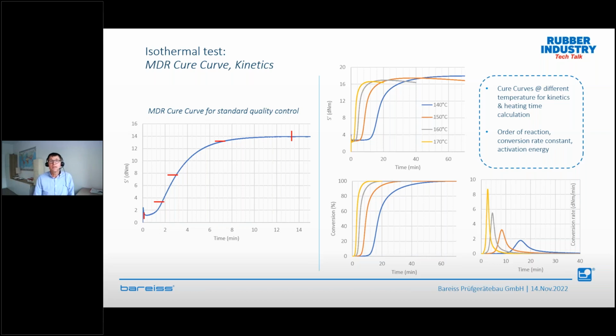But we can also run at different temperatures, and then we can calculate the conversion and the conversion rate. We can do more enhanced calculations like order of reaction, conversion rate constant, activation energy, and we can calculate the heating time, for example, of your 6 mm plates. Oliver mentioned samples which we need for hardness, or 2 mm for tensile tests and so on. We can calculate the heating time very easily.